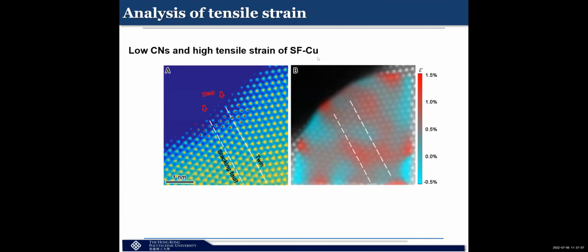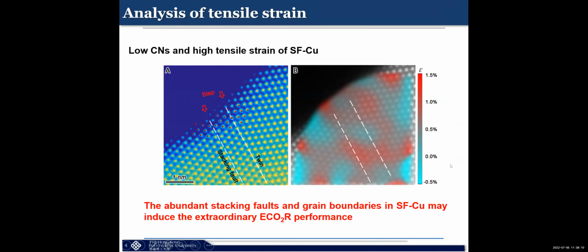Right. So we also did some analysis on the tensile strain using the TEM, and we can identify the stacking fault, the strain, and the low coordination number at the edges. From some of the strain analysis, you can see that in some regions of the particle, the strain is relatively high compared to other regions. Okay, so that also tells us our copper nanoparticle catalyst has a certain percent of tensile strain, and certain regions with a low coordination number. Both factors are very important to increase the catalytic performance, because of this abundant stacking fault.